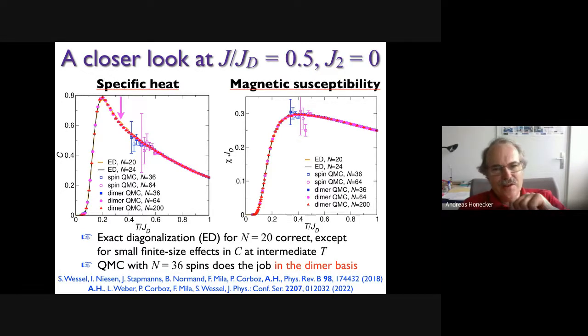If you are in a spin basis, you get an exponential blow up of the error bars as you come from high temperatures, as anticipated. So you do see that here. And well, maybe you can barely get to the maximum of the susceptibility, but that's it. You don't get into the low temperature region. So the spin basis quantum Monte Carlo is basically useless.